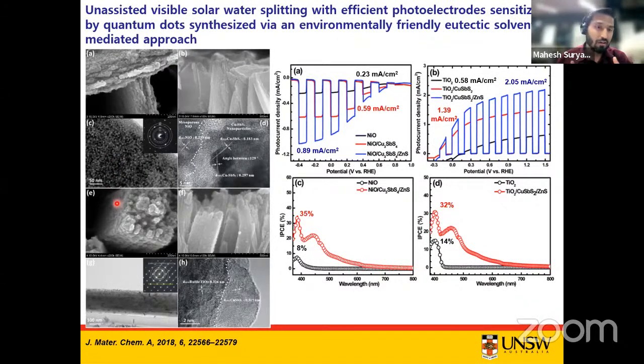So in short, we studied the band alignment, and we then fabricated the photoanode and photocathodes based on these sensitized quantum dots, and we assembled the unassisted water splitting system. When I say unassisted water splitting system, it means you don't need to provide an external potential to drive the water splitting reactions, because these 2 electrodes are capable enough to produce the hydrogen by simply absorbing the sunlight. That's because we are using semiconductor materials on both sides as a photocathode and as a photoanode.